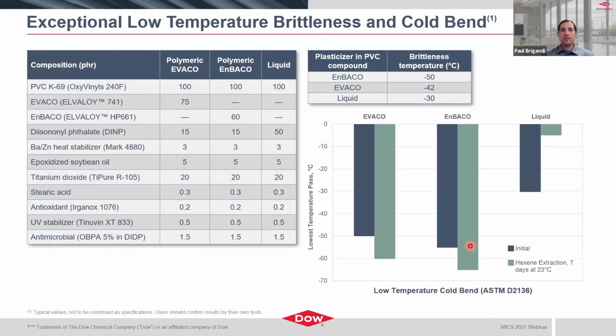So here is some data that was generated, again, somewhat of a simplified formulation or a model formulation, just to show the benefits and the performance with the polymer modifiers versus liquid. Here we're looking at a comparison of both the Vaco, so the vinyl acetate terpolymer, and the butyl acrylate terpolymer in this model composition. And what we're showing here is actually you can get much lower brittleness temperature with the butyl acrylate-based terpolymer versus the vinyl acetate, but both are significantly lower when compared to liquid in this case.